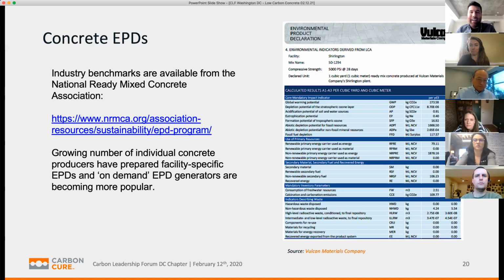And being Canadian, I appreciate that, but I know sometimes it's not so much appreciated in the US. And then down the line there, you'll see the text is really tiny, so I won't ask you to read that, but you can see that the first one on the list is global warming potential. And in this case, what you're seeing is that from this particular mix, the per cubic yard carbon content is 274-ish kilograms of CO2. So for every cubic yard, that's about the impact of CO2 coming from this mix.